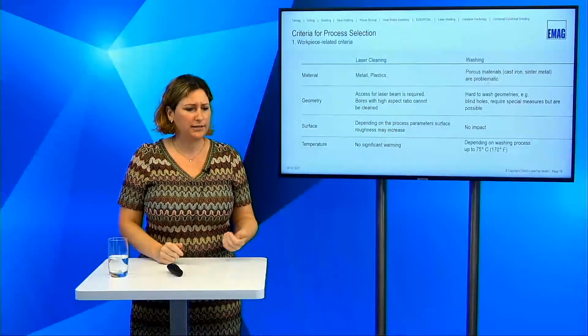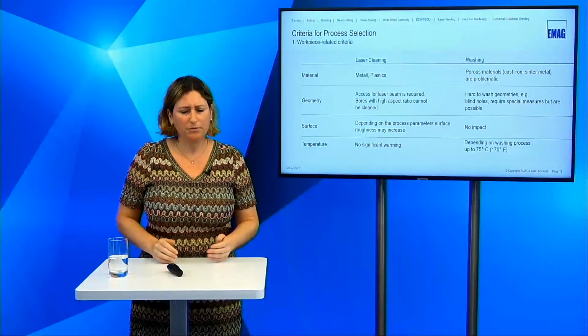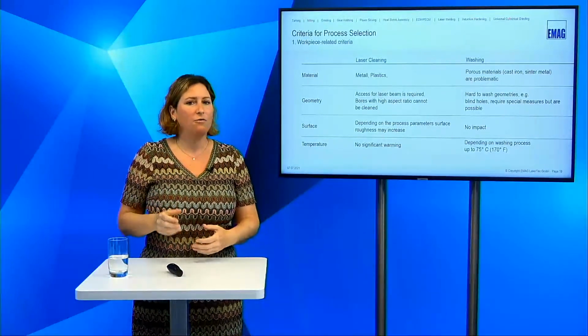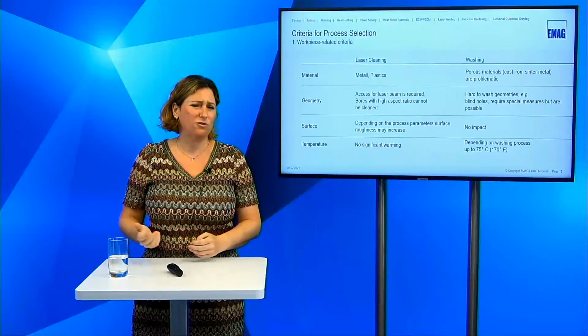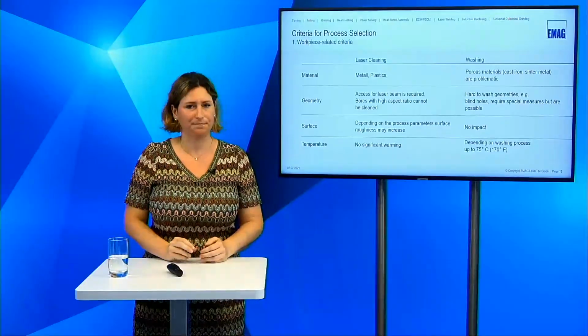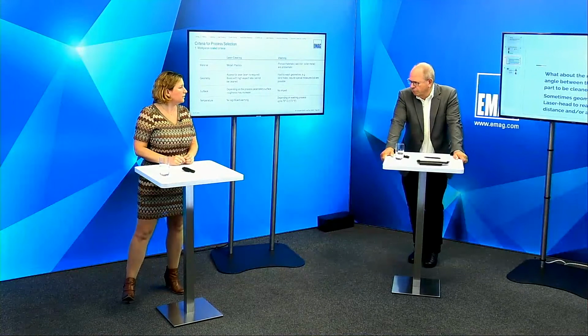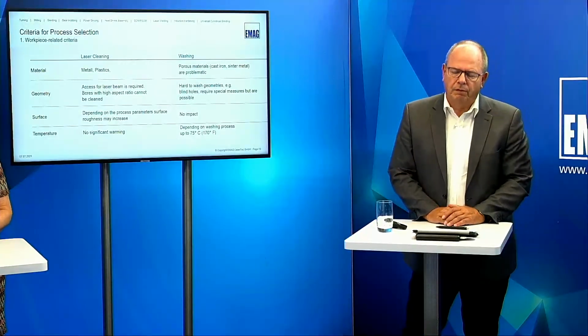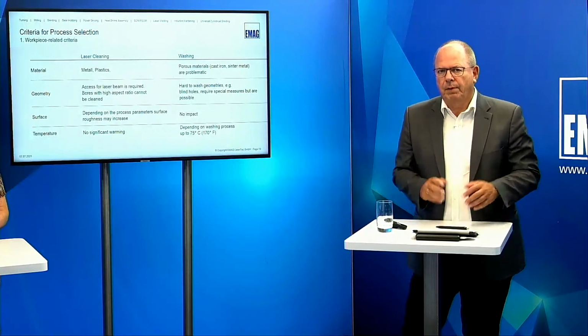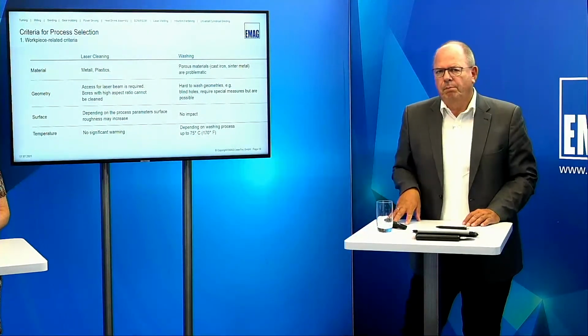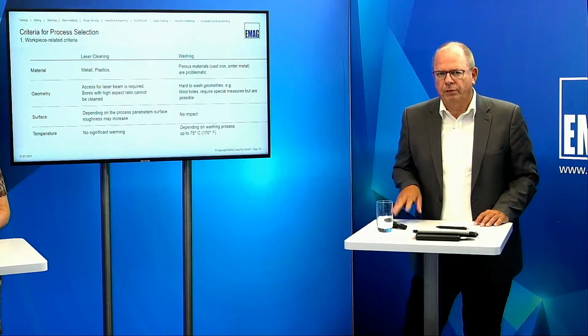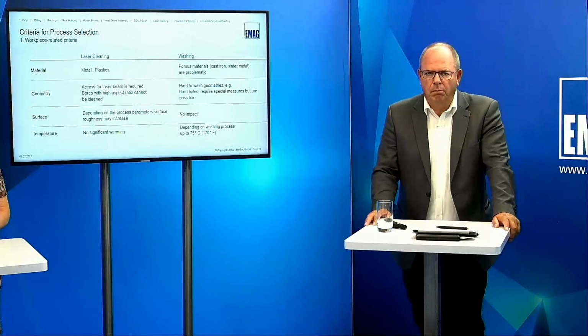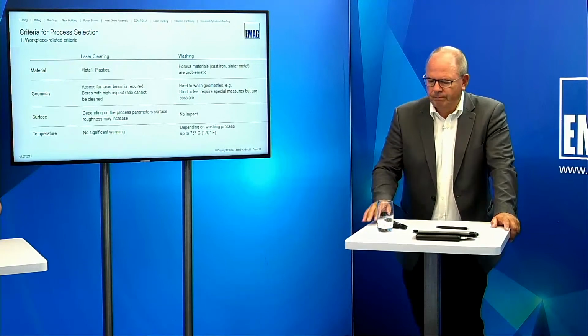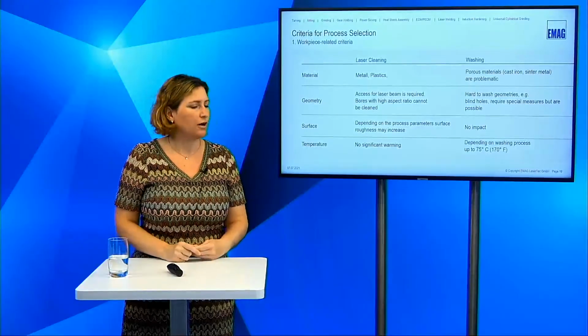So you're right, the geometry, you have to take a look on the geometry, but you have also a certain Rayleigh distance for the lasers, especially the pulsed laser systems. They have a quite good beam quality, so you have a bigger area where you really work in the focus, on the focal area. So this is the so-called Rayleigh distance, so you don't need to be exactly in the focus. I think we can compensate for some millimeters, 2, 3, 4 millimeters, depends on the optics, the processing optics, and the angle of incidence has, of course, an impact on the effectivity of the process. So if you have a non-optimal angle, you can compensate by reducing the feed rate. So you have quite some options to play with, a window, let's say. And you can also use additional mirrors to change the focal position afterwards.